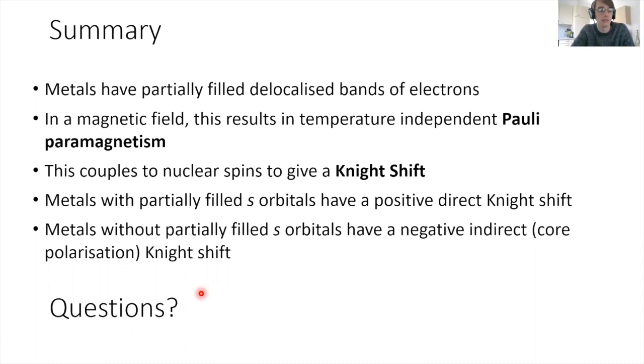The Van Vleck term is a second order term and tends to be much smaller than Knight shift terms, indirect contact or direct contact Knight shifts. But it does also depend. You can see in the second order term, the denominator had the energy difference. And in a metal, your filled and empty states are right next to each other. Due to symmetry, they're not right next to each other, but that term can get quite small, and so you can get quite large Van Vleck shifts.